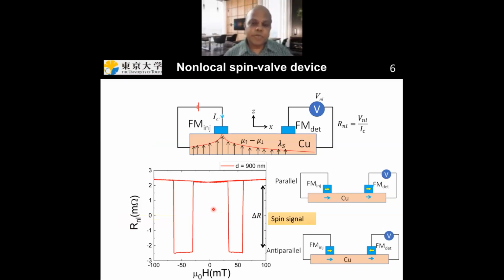So in this device, now you have created a spin current, how can you detect it? You can detect it by putting a voltmeter at the other ferromagnetic electrode and the copper. In this case, you will detect a voltage, and you will detect it because at this end you apply voltage and create a non-equilibrium spin accumulation. At the other end, there is also a non-equilibrium spin accumulation. Due to the reverse process, it will produce a voltage, and this voltage we call the non-local voltage. Note that this voltage is not due to the charge current, because charge current is only flowing in the circuit over here.